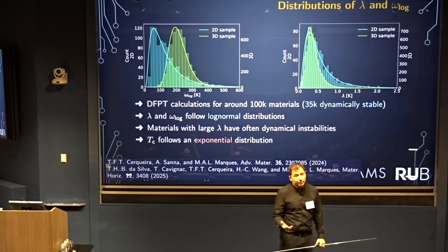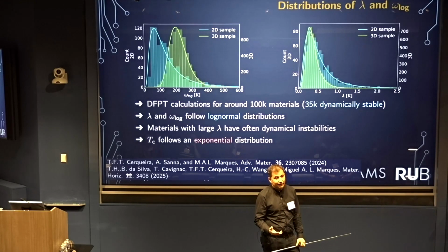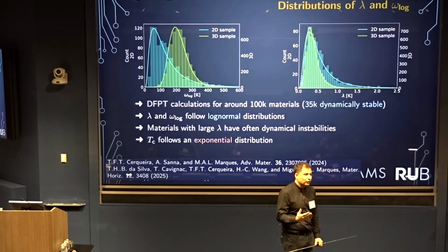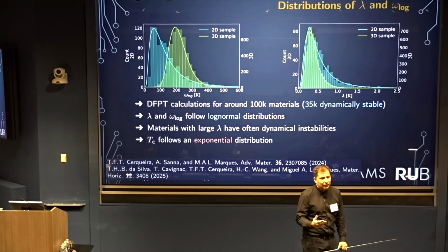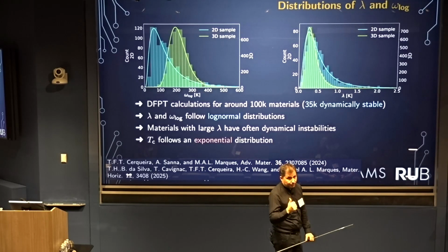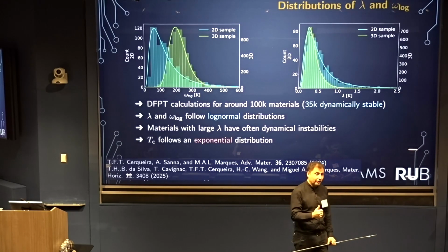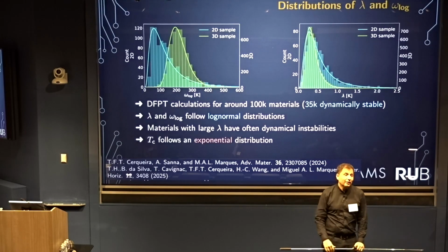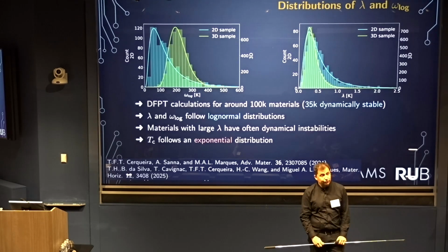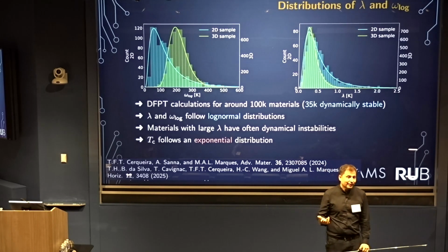Now, I can tell you, because we did a lot of compounds and we looked at a lot of experimental data, that we have to make a lot of effort to understand even simple compounds. I give you an example. Probably 20 to 30% of the compounds that have an experimental TC give imaginary phonon frequencies to start with. Now, I'm sure Ion will be able to solve most of those problems with anharmonic effects, but we don't have them, right?